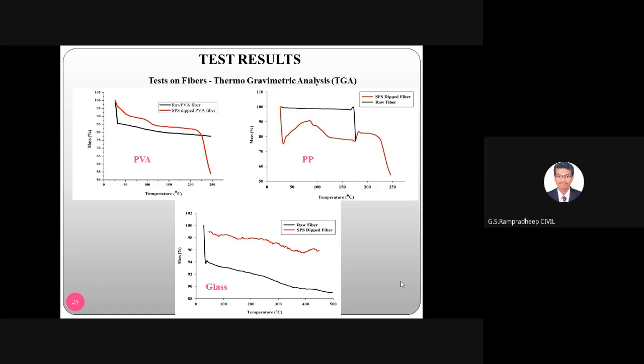So you can see the different types of TGA analysis. For example, if you take a sample for the first fiber, PVA fiber, right? The mass percentage at a temperature of around 30 degrees is 100. And finally, as the temperature increases, your mass percentage is around 55. So there is not much difference, not many deviations that we can observe for all these graphs using the